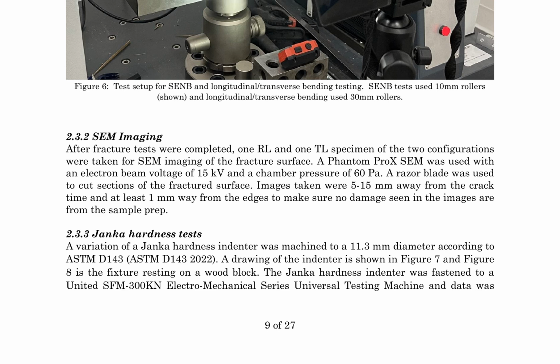Complementing the fracture tests, Janka hardness tests were conducted using a custom-machined indenter conforming to ASTM D143 standards. The indenter design and fixture setup are depicted in Figures 7 and 8. The indenter was attached to a United SFM 300KN electromechanical series universal testing machine to collect data, providing a comprehensive understanding of the material's hardness and resistance to indentation.